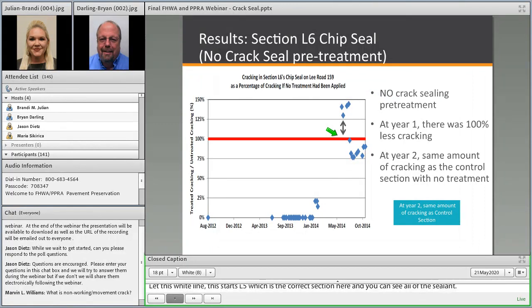So in the next section, L6, they did a single chip seal. In this treatment section, they did not crack seal first. They just came out, cleaned, and put down a single layer chip seal. Now, it performed awesome through the first year. You can see all the data points here on the bottom line. It was performing at 100% after that first year and that first season.